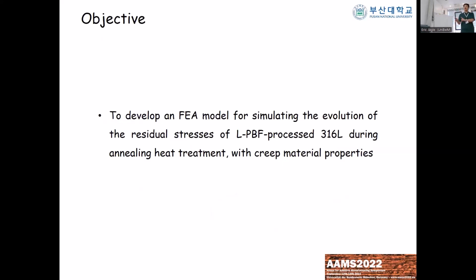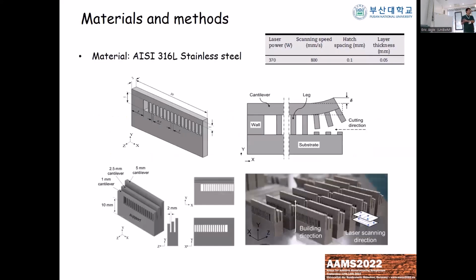We started this work first with the very common material, 316L stainless steel fabricated by powder bed fusion. The material was 316L, and we used different laser parameters with the Japanese Sodick laser system, which is a replication of the Concept Laser M2, so the specifications are more or less the same. And we didn't actually change the parameters for this research. We just used all parameters that are recommended by the manufacturer of the machine.